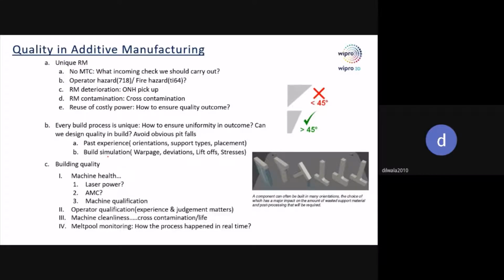You should be aware by now that it takes like 20 hours to 20 days to print a part, depending on the part complexity, layer thickness, and part height. Say, for example, after running the machine for 20 days, you end up with a machine breakdown. Then customer delivery will get affected, the part will get rejected, the order will get missed, and the machine hours that were spent building the parts will get wasted. It becomes a very costly affair.